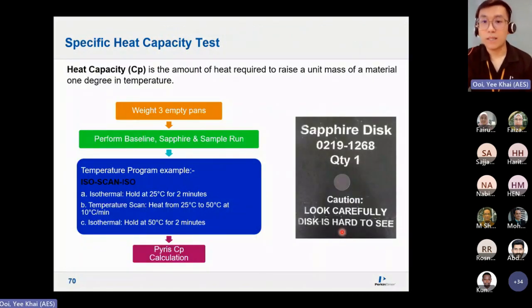For those doing specific heat capacity, we use a three curves method. You need a Sapphire standard, which has a known specific heat capacity. We need to run three runs: one is the baseline run, one is the Sapphire, and one is the sample run. The temperature program must be ISO, scan, ISO, depending on your temperature range, with two isothermal steps at the initial and the ending of the run. Then you fit all three curves into the software, and it will calculate the specific capacity for you.